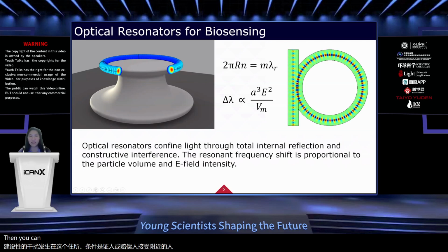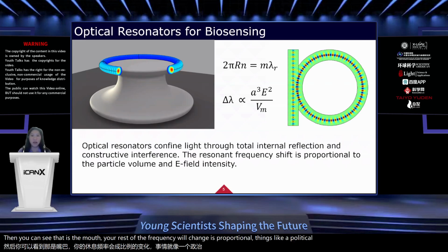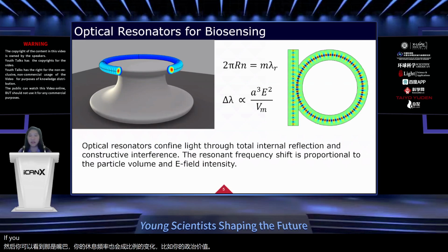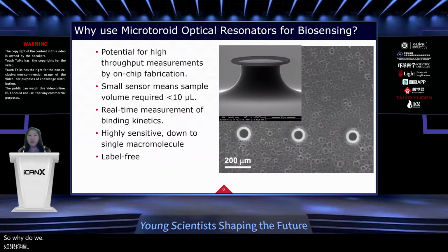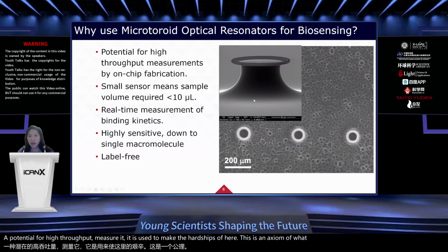And you can see that the amount your resonance frequency will change is proportional to things like your particle volume and your E field intensity. So why do we use microtoroid optical resonators for biosensing? One is that they have a potential for high throughput measurements because you can make them on chip. So here, this is an SEM of what the toroid looks like. You can see they're about 100 microns in diameter.